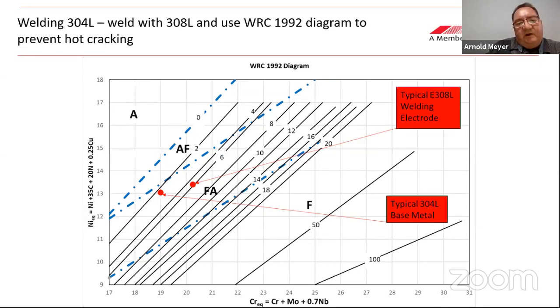this is a diagram developed actually by Damian Kotecki and others. It's called the WRC 1992 diagram. And you can plot your nickel equivalent and chromium equivalent onto this diagram. And where you basically should be is in the FA region of this diagram. That means that a little bit of ferrite will form first, and that will protect your grain boundaries against the hot cracking. If you look at where the 304L is, it is very close to the lower boundary, and that's not where you want to be.